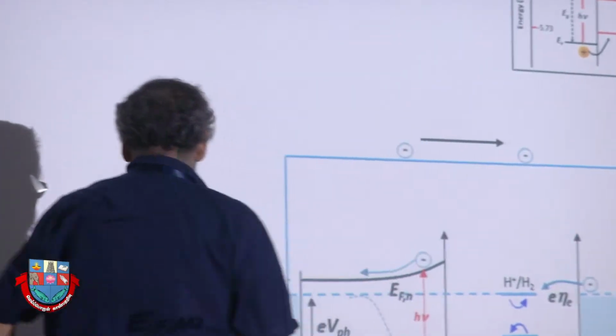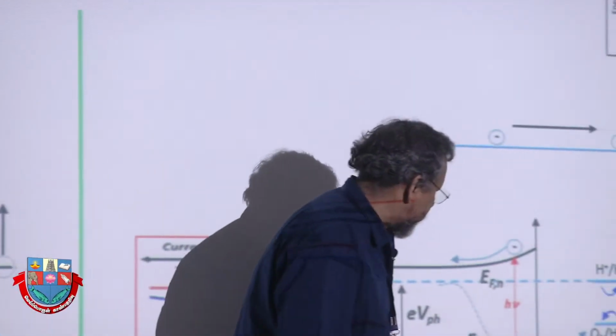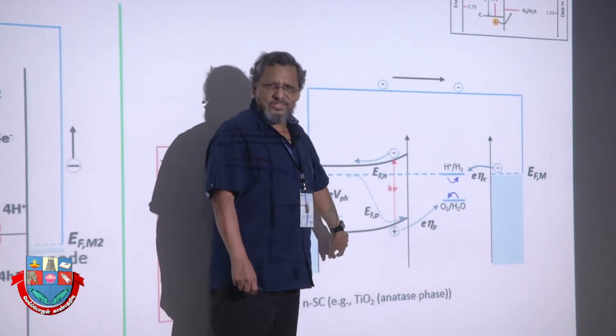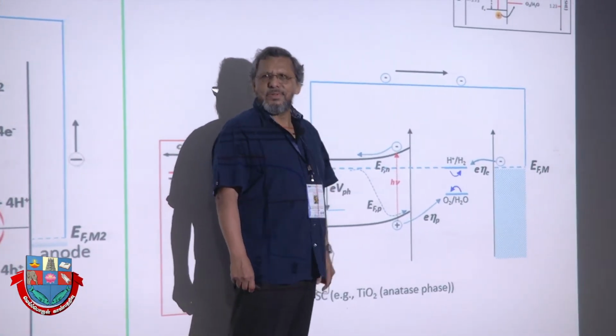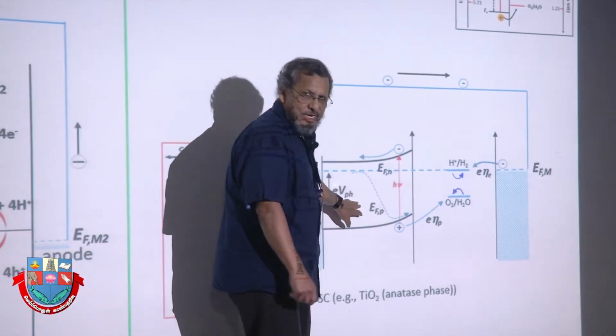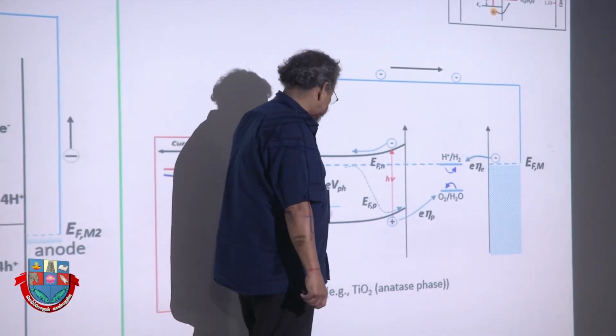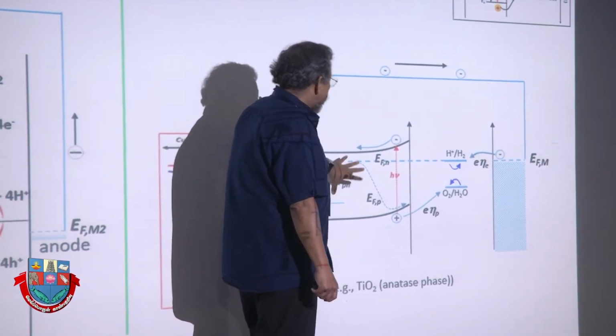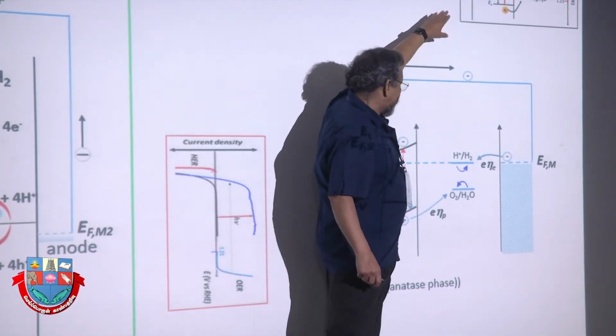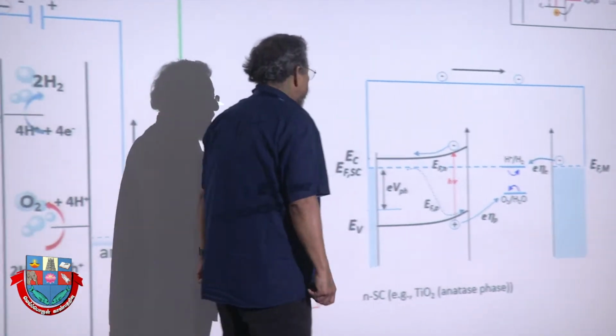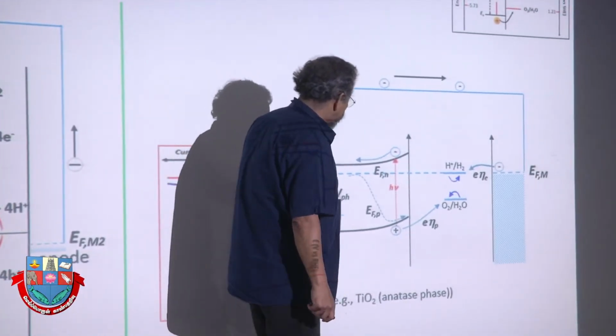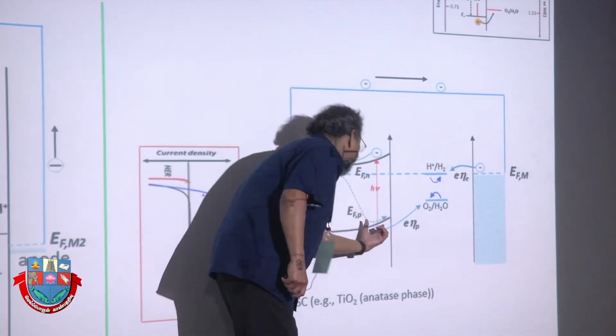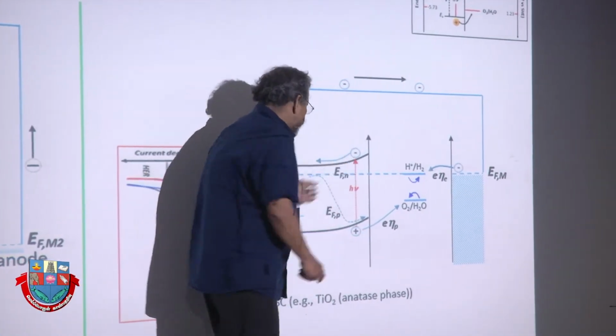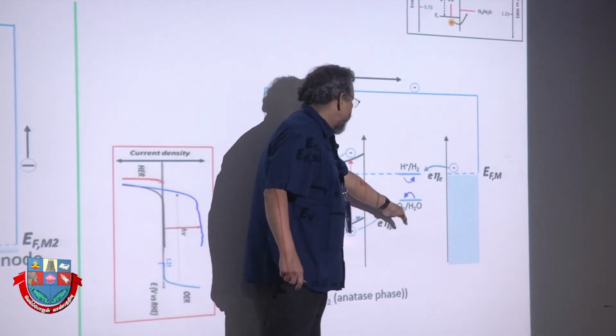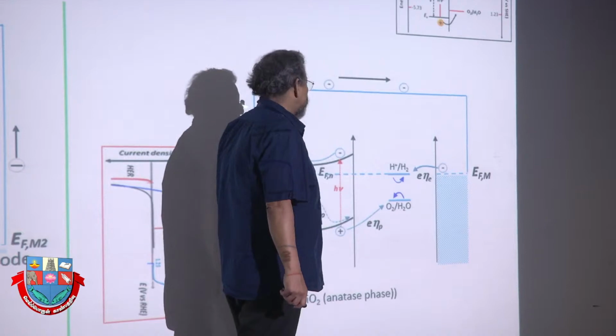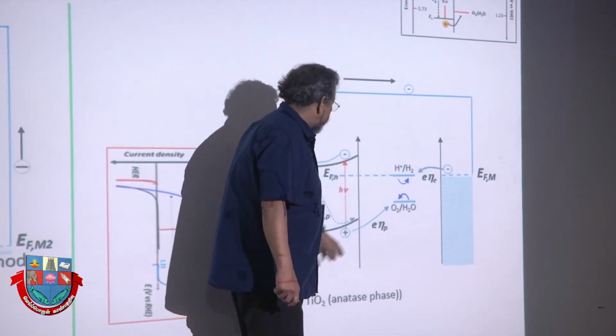Okay? So, here is a nice experiment published in the 70s by the Japanese group, but they used rutile as material. Here we work with anatase, okay? So this system more or less obeys what I said here. There is a straddle of this energy, but here is a photoelectrochemical system because here you create a special region in which you create an electrical field that will be able to separate the charges. So holes will be conveyed here, and the electron will go to the counter electrode to make the hydrogen evolution reaction, and here the oxygen evolution reaction.